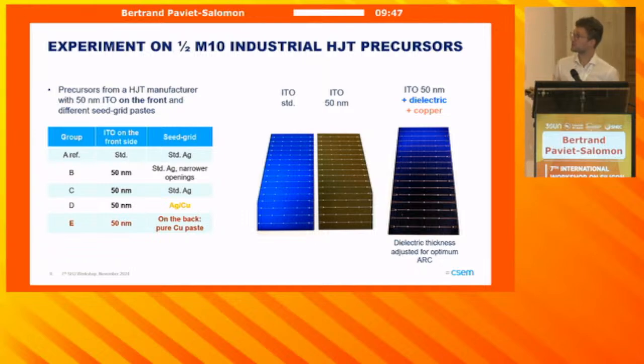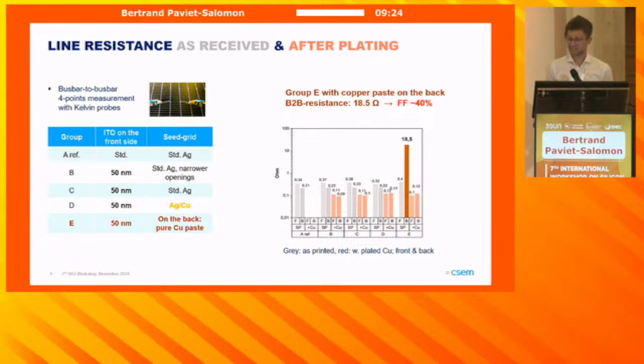You can see on the picture that as received, the samples feature a typical brownish appearance because the ITO is too thin to perform a good anti-reflective coating. But on the right, you can see that once we completed the devices with the masking layer plus the copper plating, we fall back on a much more standard blue color, which indicates that the anti-reflective coating is pretty good. Let's have a look now at how the line resistance evolves in the as-received state versus after plating. If you first look at groups B, C, and D, the ones with either the standard silver paste or the SCCPs, you can see that after plating we have a twofold reduction of the line resistivity, which is very well expected.